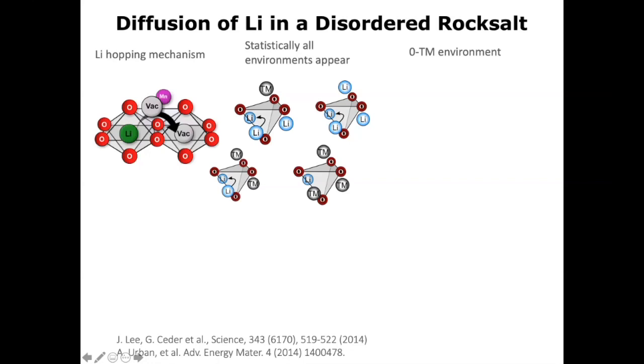So if the lithium slab spacing contracts, then the activation energy goes up because when lithium diffuses in here, we have more of a repulsion with the transition metal and the kinetics degrades. You don't have this if you could make this channel. So if you could make a tetrahedral activated state where there's only lithium, then this side and this side would be vacant in a diffusion process. So when the lithium goes in, it only face-shares with another lithium.